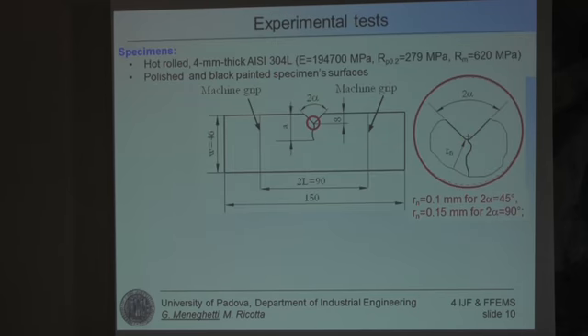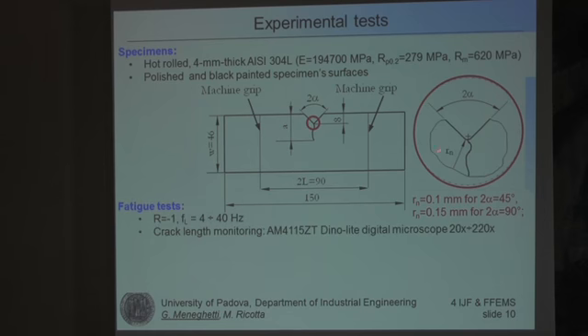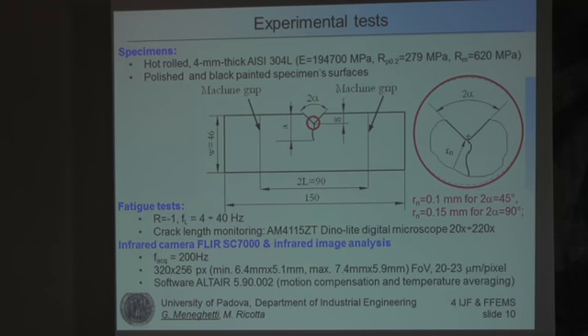We took the material we had tested in the past, which is a hot rolled 4 mm thick stainless steel material, 304 low carbon. We polished the surfaces of the specimens, and we black painted one specimen's surface, while the opposite specimen's surface was monitored by means of an optical microscope. So the crack starter was a sharp notch with two different notch opening angles and a reduced notch tip radius of 0.1 or 0.15 millimeters. We performed the fatigue tests under a load ratio of -1, and we monitored the crack length by means of a digital microscope. On the opposite surfaces, we monitored the temperature field by means of an infrared camera.